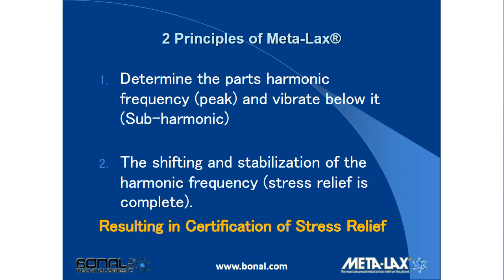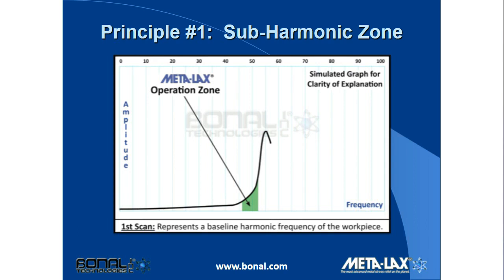There are two principles in Metalax. We know that all parts have a harmonic frequency, and if there is thermal stress in a part, that frequency is out of phase. Principle number one: find that part's harmonic frequency and vibrate below it in the subharmonic zone. Metalax induces vibration into the part, obtains a harmonic curve, and then applies vibration below that harmonic peak in the subharmonic zone for usually 15 to 60 minutes, depending upon the size, weight, and material of the part.